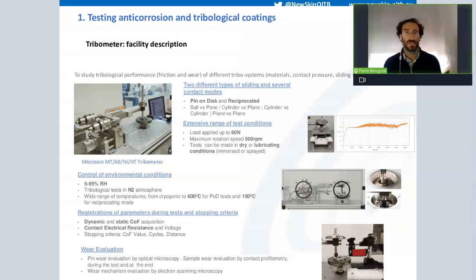We can test in a wide range of conditions with loads up to 60 newtons, maximum rotative speed of 500 RPMs. We can also test with different lubricants, under nitrogen atmosphere, and a wide range of temperatures as well. With this data, we can extract very valuable information for the selection of lubricants, or for the selection of coatings and substrates that will be applied in the industry.